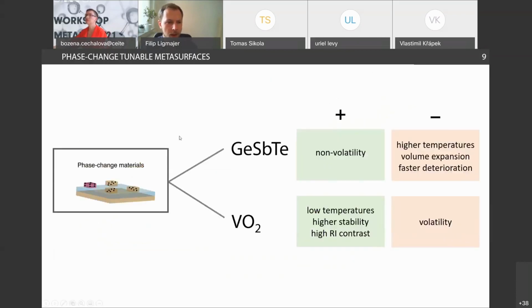And the last approach which I would like to focus on today is the approach involving phase change materials. There are more phase change materials available, but most of the applications today are based on either of these two. So it's either germanium antimony telluride, or vanadium dioxide. Both of them have their pros and their cons. GST, as it is abbreviated, is non-volatile. That means that even after you stop influencing, its properties stay the same. That's the reason why it was used in rewritable CDs, which is something the older audience can know, and maybe younger ones do not. But it has some disadvantages as well.